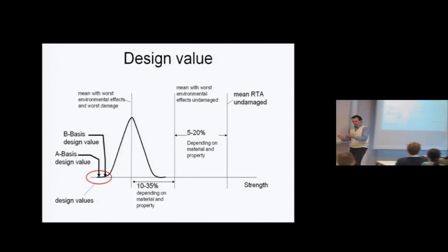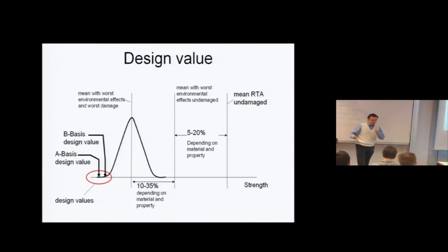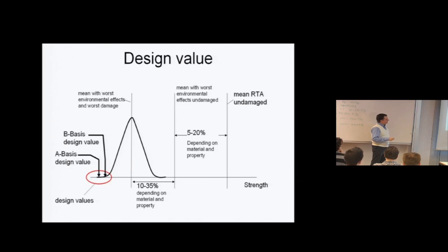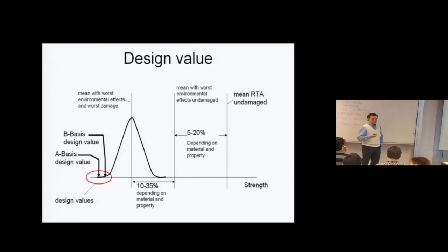So if I take everything together, I will completely destroy this wonderful material that has these excellent properties. Basically, my strength at room temperature ambient undamaged is somewhere out here. And that's the mean value. Now, I have to reduce this from here to here, 5 to 20%, to account for the worst environmental effects. 5 to 20 depends on the property, depends on the material, depends on the environment you are taking into account. So you're down here, and then you further reduce it to include the worst type of damage. Typically, it's impact damage. And that gives you the mean strength accounting for environment and accounting for damage.